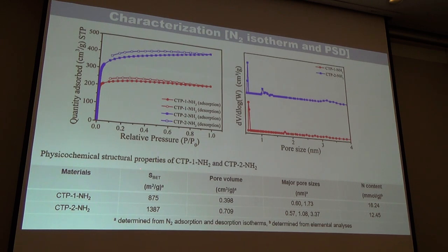Further, the pore surface properties of these two materials are analyzed using N2 adsorption-desorption isotherms. Both materials show type 1 isotherms, suggesting that they have a high level of microporosity, and the pore size distribution is calculated using the NLDFT method. As you can see, both are highly microporous, whereas CTP2 shows slight mesoporosity at 3.37 nanometer.